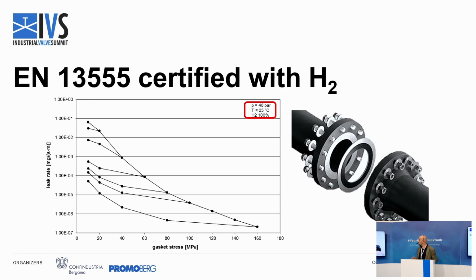And it recreates the condition of compression and relaxation on a gasket in a flange connection. This is the flat gasket, the flange connection. And we recreate the same test using 100% hydrogen with the same temperature and same pressure. We discovered in differently than the compression packing, which is a dynamic sealing. This one is basically a static sealing. Of course, there's the compression and relaxation between the valves, but there's no movement. So this is a static flange, a static seal.